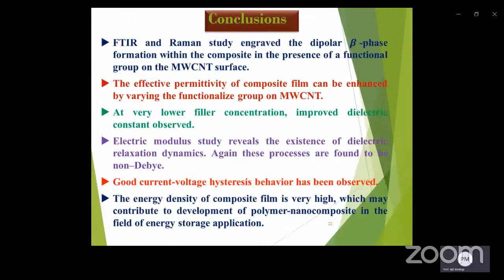In conclusion, FTIR and Raman studies suggest the formation of polar beta phase of PVDF in the composite. Enhanced dielectric property has been observed with ferroelectric hysteresis loop. The energy density of the film is very high, so it can be used as energy storage material.